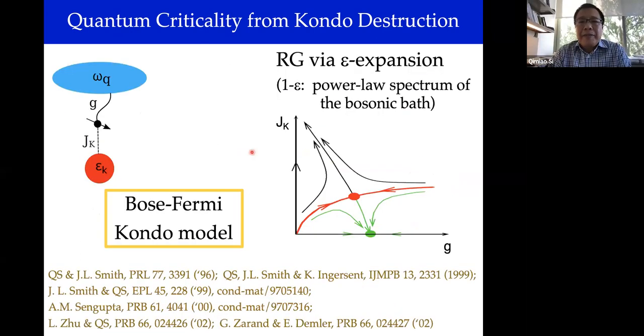Okay. But what I was going to say is that this procedure allows us to address the fate of local moments in the different parts of the phase diagram, because the local moment coupled to the fermion bath leads to the Kondo state, and there's a renormalization group procedure that one can apply to analyze this Bose-Fermi Kondo model. So there's this Kondo fixed point, but if you tune the coupling to this bosonic bath, which reflects the effect of RKKY interactions, you can destroy this fixed point and reach another type of fixed point.